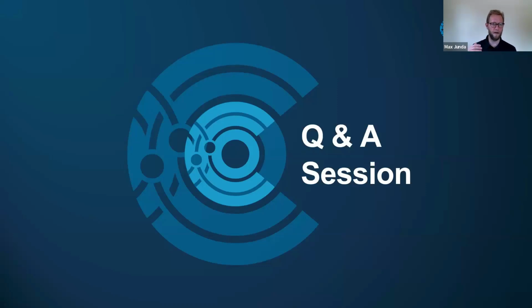So I'm going to assume that basically means we have a multi-layer stack, and we basically know all the information about those underlayers, and there's a thin surface layer, and we want to determine properties for that. In principle, that is doable. However, the key thing is that, as I showed with the examples of increasing film thickness and how the spectrum becomes dominated by a lot of what I'll call wiggles, in order to measure the properties of a very thin film that's on top of a multi-layer, and particularly if some of those layers can be pretty thick relative to the surface film, we are going to need to be able to have a very accurate optical model.